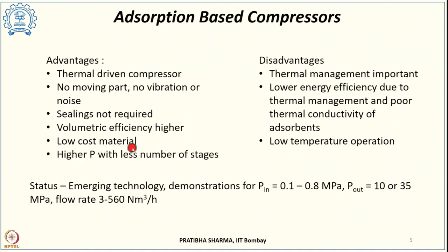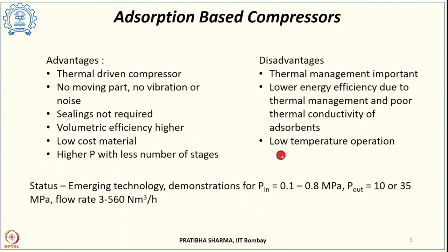Both capex and opex costs are lower. Higher pressures can be achieved using these devices with fewer stages. But the major disadvantage is that thermal management becomes very essential — both heat removal and heat supply mechanisms are needed to maintain a uniform bed temperature. Lower efficiency results from poor thermal management and the poor thermal conductivity of the adsorbents used.